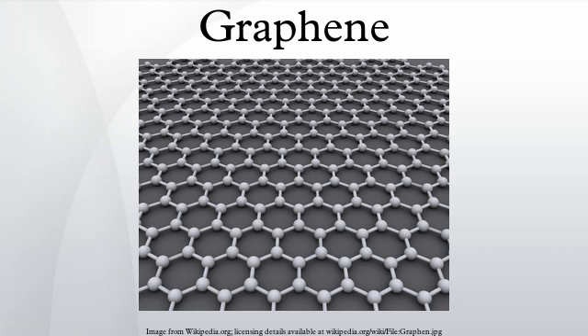Chemical: graphene is the only form of carbon in which each single atom is in exposure for chemical reaction from two sides. It is known that carbon atoms at the edge of graphene sheets have special chemical reactivity, and graphene has the highest ratio of edge carbons. In addition, various types of defects within the sheet, which are very common, increase the chemical reactivity. The onset temperature of reaction between the basal plane of single-layer graphene and oxygen gas is below 260 °C, and the graphene burns at very low temperature. In fact, graphene is chemically the most reactive form of carbon, owing to the lateral availability of carbon atoms.